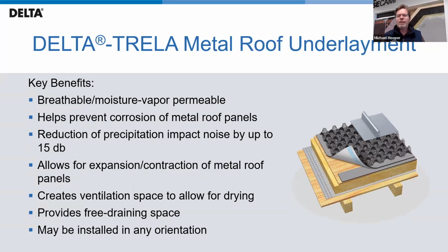So the advantage in using a product like this under metal roofing is metal roofing being impermeable doesn't allow the substrate, the sheathing underneath, to dry. This creates that air gap and convective airflow in order to dry any moisture that does get through to the lower deck. In doing so, it minimizes the corrosion of the metal roof panels, as well as the fasteners that are used for the sheathing itself.